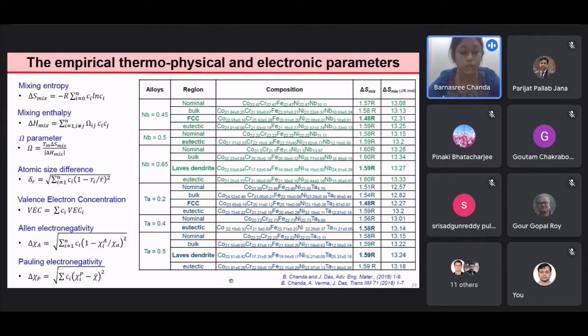The phase prediction and the phase stability have been studied considering various empirical, thermo-physical and electronic parameters such as mixing entropy, mixing enthalpy, omega parameter, atomic size difference, valence electron concentration and electronegativity parameter. The mixing entropy of individual phases and the bulk region satisfy the definition of the high entropy alloy, that is 1.5 R.